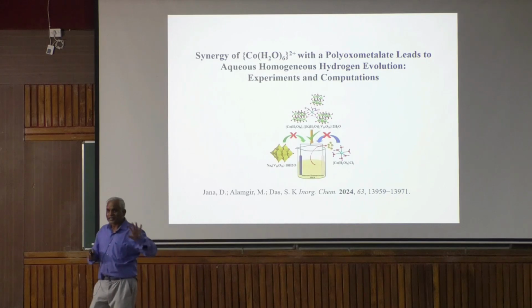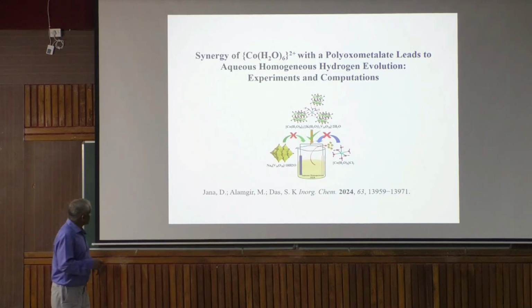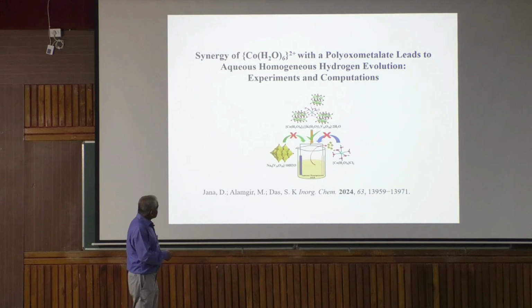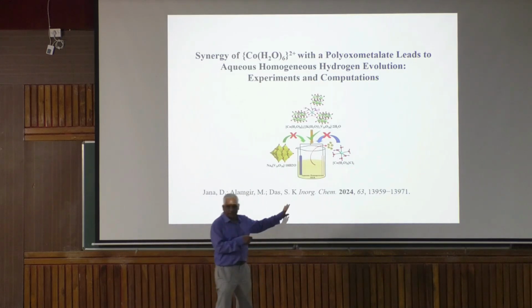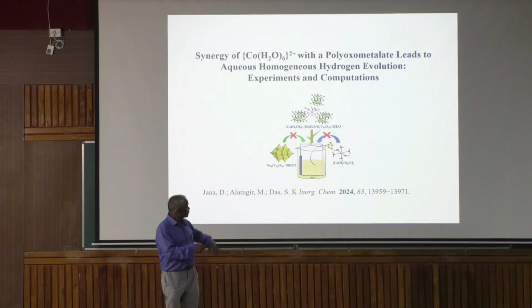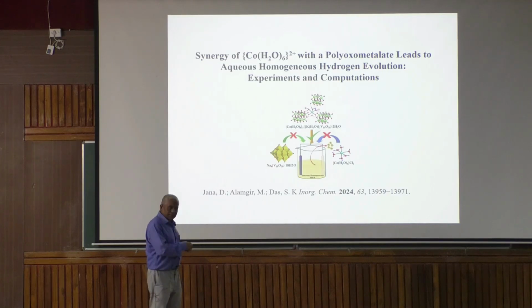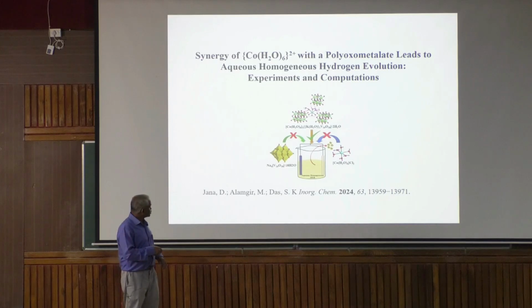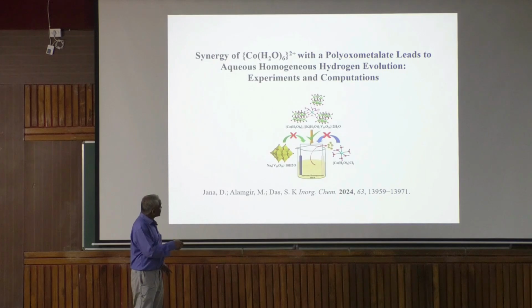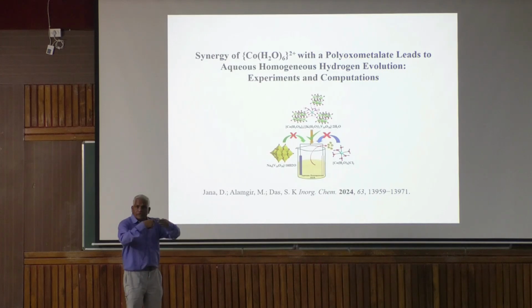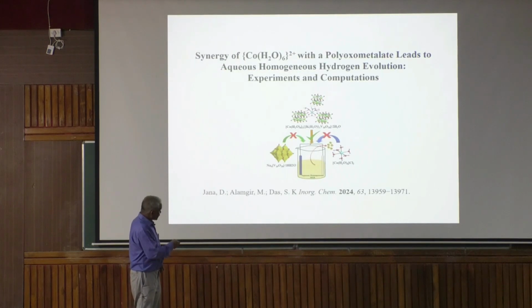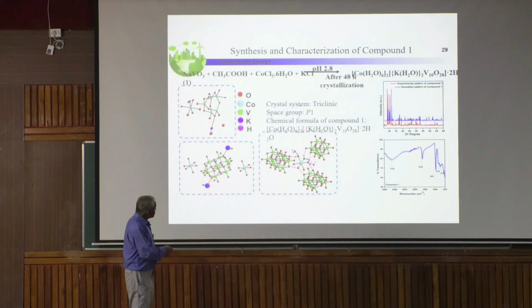Because this system, when I explain, may confuse, I am telling you again and again that this compound doesn't give water reduction, this compound doesn't give water reduction. In fact, we already know this compound, if you take this, it gives water oxidation. I told you already, the cobalt oxide form. This can, in principle, give hydrogen, because vanadium 5 goes to vanadium 4 and gives hydrogen. We checked, it doesn't give. The whole compound gives. But again, there is no coordinate covalent bond, only hydrogen bond. The hydrogen bonding I am showing here.